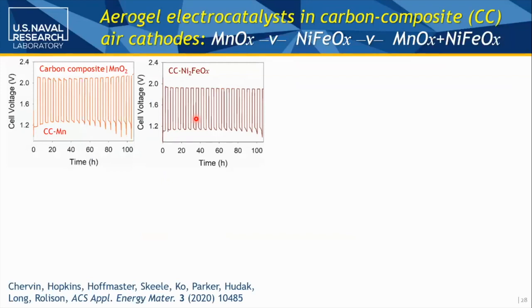We've made 2 types of catalysts, the cryptomelane tunnel structure polymorph of manganese oxide, and a nickel ferrite, which is known to be a reasonable oxygen evolution catalyst. Cryptomelane is better for oxygen reduction. And we've gone to carbon composite because everybody else uses that and we can compare our results. Just the manganese oxide, you can see you've got a reasonable discharge cell voltage, but you've got to charge it well above 2 volts, and carbon doesn't like to go there.